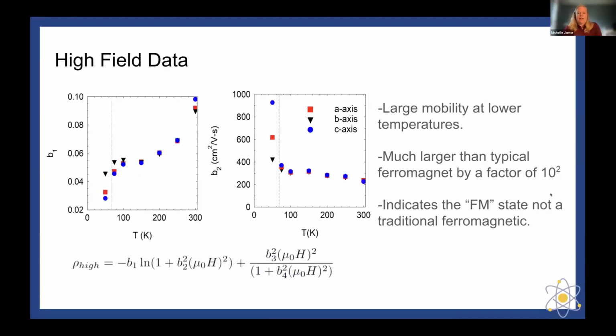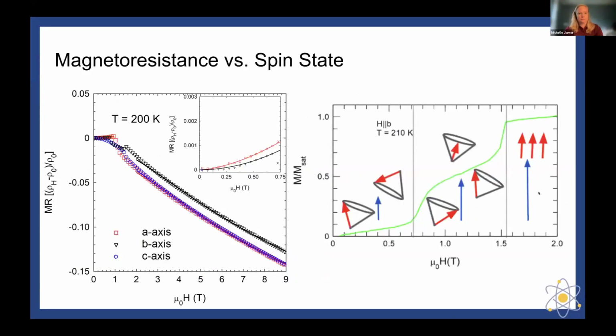So what we see is that we have a much larger mobility than a typical ferromagnet by a factor of 100. And what this really indicates to us is that the ferromagnetic state is not actually a traditional ferromagnet. So by using the magnetotransport data, we were always thinking that this ferromagnetism that we note in the low temperature range is not quite a true ferromagnet. It just behaves kind of similar. Even if you were to look at the magnetization curves, what you'll note is that you have a strong linear slope to the magnetization and then a sharp saturation, which is a little bit unique.